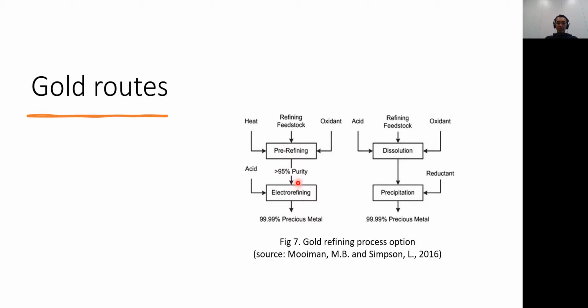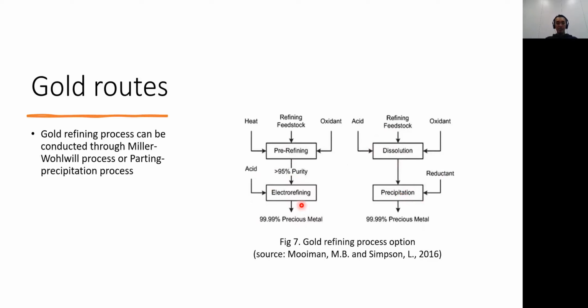When the gold has a higher than 95% purity, it will go to electrorefining, and usually they use aqua regia as the medium there to produce precious metal, 99.99% gold. Another route is that the bullion is dissolved by adding aqua regia with some oxidant, and the gold is leached there, and then it is precipitated with some reductant, for example SO2 gas or some kind of cementation process, to produce 99% precious metal.